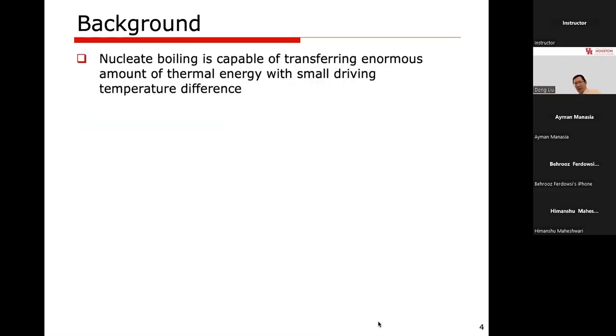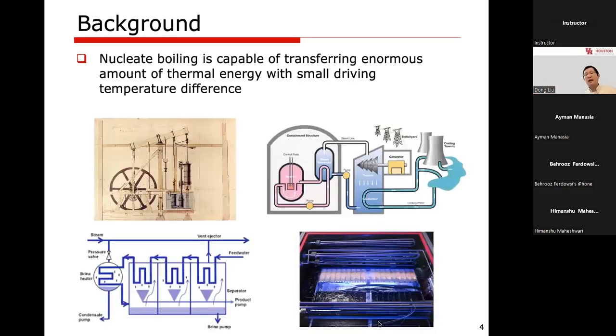So from this, you can tell nucleate boiling is appealing, especially because it is capable of transferring an enormous amount of thermal energy with a very small driving temperature difference. So ideally there's no temperature rise at all. If you maintain the process at 100 Celsius at 1 atmospheric pressure, you can transfer a lot of energy. So that is why it has been heavily used in industry, right?